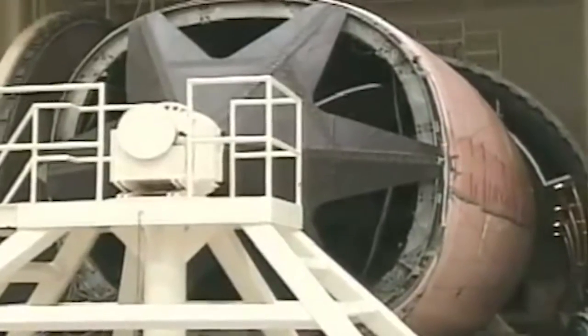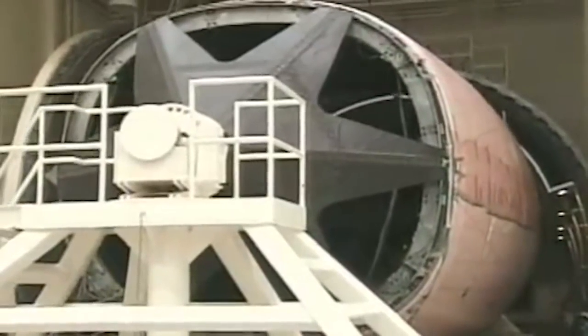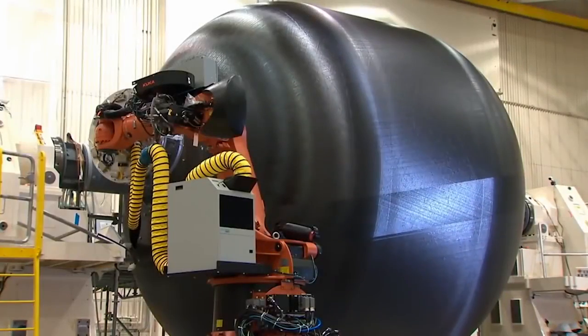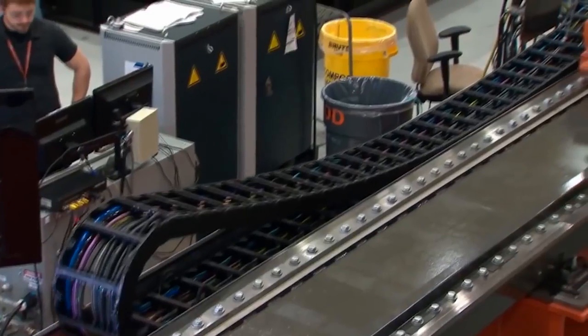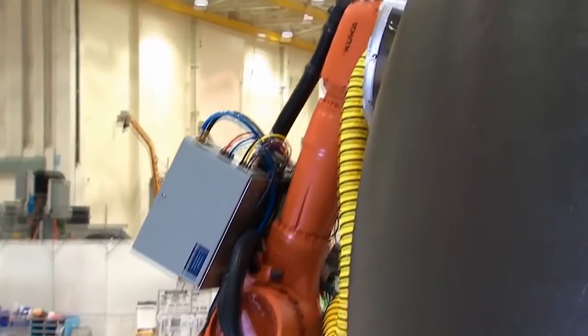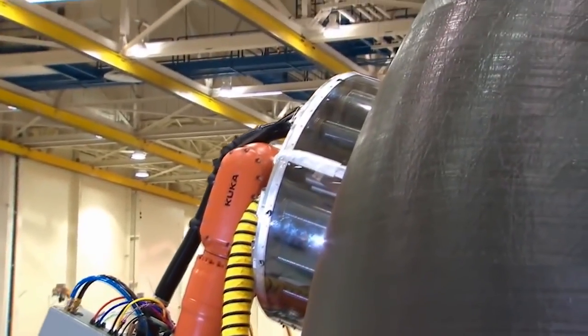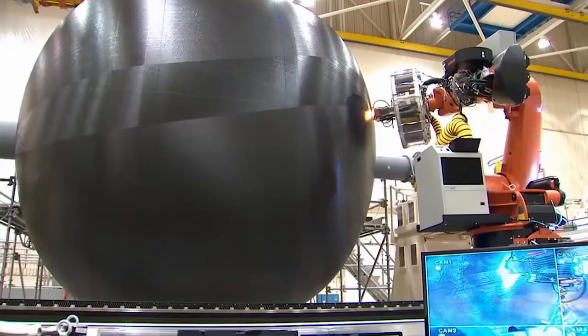The autoclave Boeing uses for the Dreamliner is massive, and there isn't an autoclave in the world big enough to fit the tank SpaceX created. It's hard to know how they did it, but they almost certainly used an automated tape placement robot, like the one Boeing used to create their own smaller cryotanks, which can cure the resin with a laser as it lays the pre-preg carbon fibre tape down.